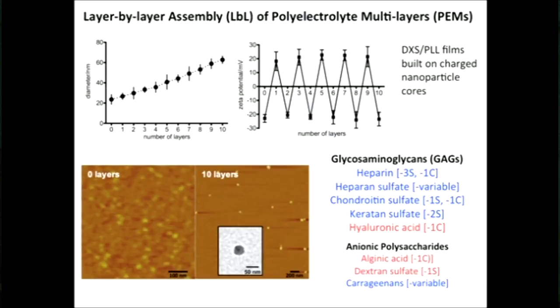We can also measure the charge on these systems. They start off negative, go positive, negative, positive. Nice alternation between plus and minus with each deposited layer. A sign that we are building up these materials. And it's hard for you guys to see this, but the quantum dot is tiny, but you can see a little quantum dot core with a kind of less dense polymer shell in that micrograph.